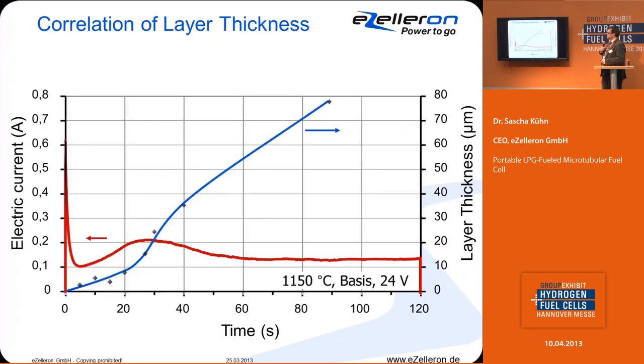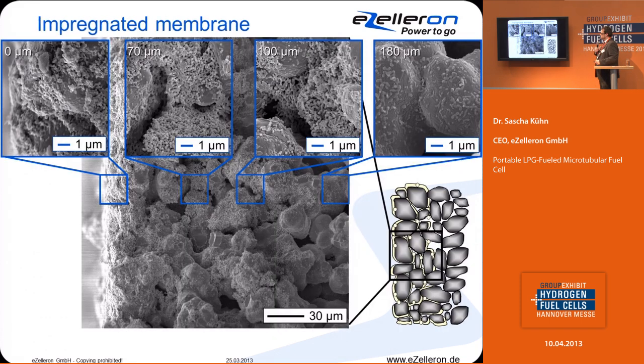You have to control the powder habitus. You have to correlate the layer thickness with the electric current during the electrophoretic deposition. Because we are heading for layers thinner than 10 microns, the deposition time has to be below 20 seconds, which means again it is possible to manufacture very cheaply. And this shows you an impregnated membrane.